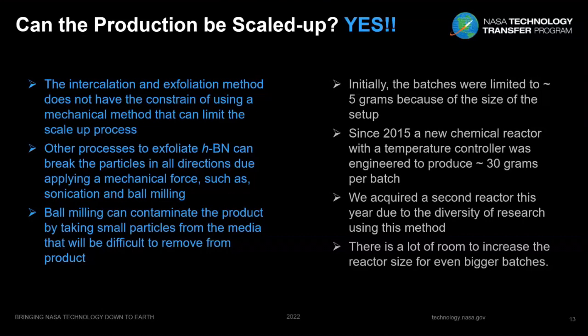Initially our batch was limited to 5 grams, because of the size of the setup that we had at that time. But since 2015, a new chemical reactor with temperature controller was engineered to produce more than 30 grams per batch. That was a huge increase. We recently acquired a second reactor to do the diversity of research using this method, because we are so overwhelmed with all the different products that we can create and so many others that we want to try. So we needed another reactor. We need more manpower too. But there's a lot of room to increase the reactor size for even bigger batches.